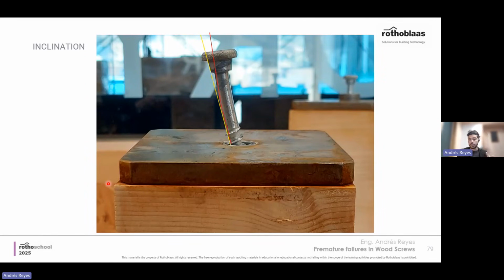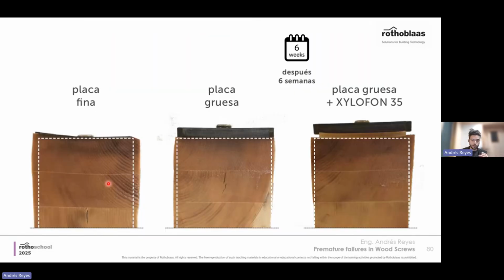And this is one of the cases of inclination. In one case, we took the screw out, and you see that with not that big of a misalignment, you could even perceive the bending, the permanent plastic deformation of the screw. So these are the final results after 6 weeks. This is what they look like. The thin metal plates have this type of deformation, which is considerable, but you see that even the plate deforms. So that means that the screw doesn't take all of the load given by the deformation.